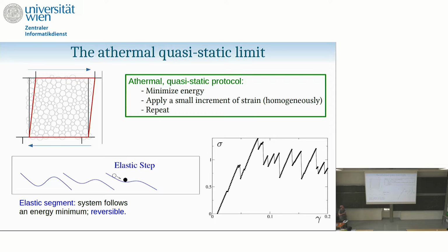So when you deform continuously your minimum, you can go back. And if you go back, you're sure to revert to exactly the same location. So the point is that so long as you distort a local minimum continuously, the response is adiabatic. It's completely reversible. So there is a single thing that can happen to introduce irreversibility. If you load your system, you will increase the energy of the system. You will increase the stress. And so the system will be in a state which is increasingly stressed.